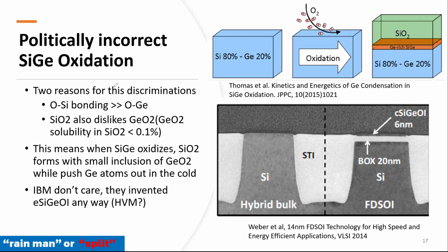On top of that, germanium oxide will not dissolve in the SiO2 matrix. Once silicon oxide forms, it kicks the germanium oxide out. The solubility is less than 0.1%. So with these two, you get a problem. This means that when SiGe oxidizes, SiO2 will form with small inclusions of GeO2. So this means SiGeOx is formed at the interface in pretty much the whole layer. So what do we do with that? Well, it's okay. They could do something.